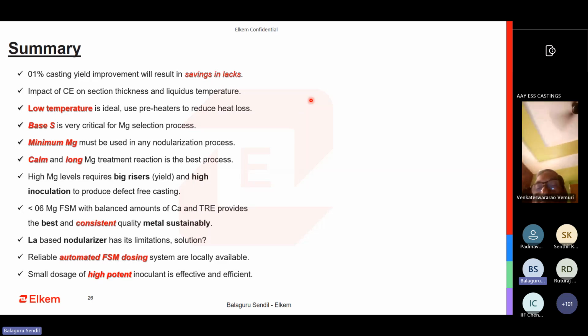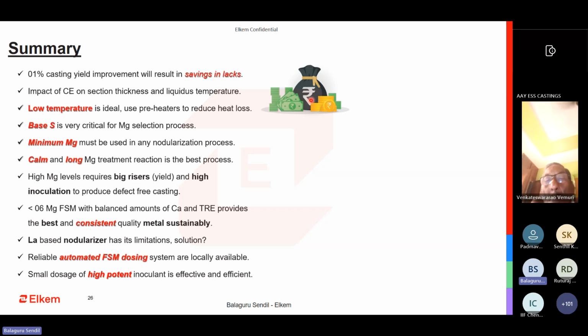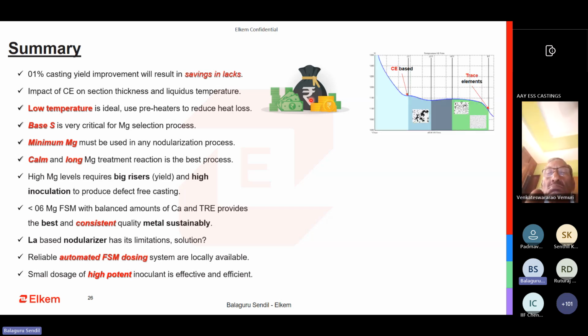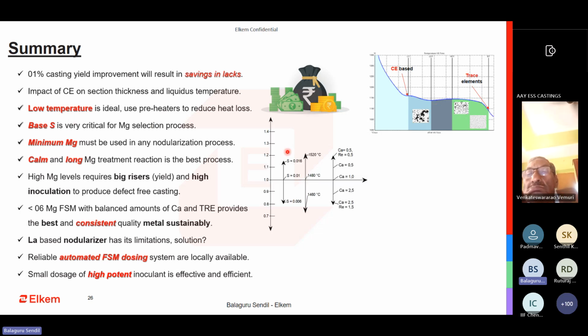Quickly to summarize, a 1% casting yield results in savings in lakhs. You can do the calculation. If 80,000 is your per metric ton cost of production, 1% is 800. So you melt 200 tons and then you calculate how much is the money. It is huge. So carbon equivalent is very important. Moving the liquidus temperature either this direction or this direction either reflects in macro shrinkages or diffuse shrinkages. It's very, very important. And lower temperature is ideal.